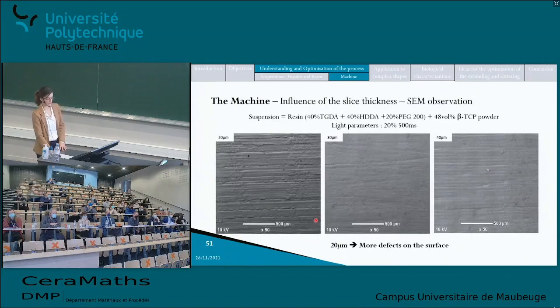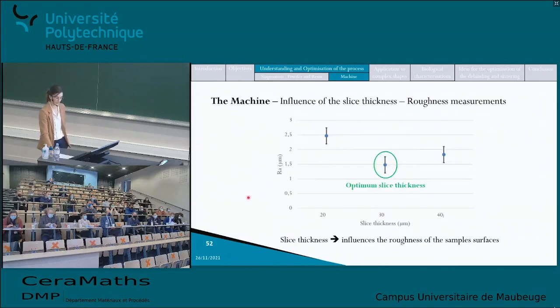Here it appears on the SEM observation that the surface of the sample printed with 20 micron seems to be rougher than the surface of the samples printed with 30 micron and 40 micron. So there are more defects on this surface. And this was confirmed with the roughness measurements. Actually, the surface of the sample printed with 20 micron had a higher roughness than the samples printed with 30 micron and 40 micron. So the slice thickness can influence the roughness of the sample and therefore the appearance of defects on the sample and the decrease in mechanical properties.